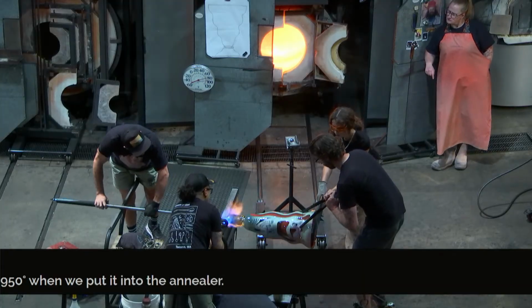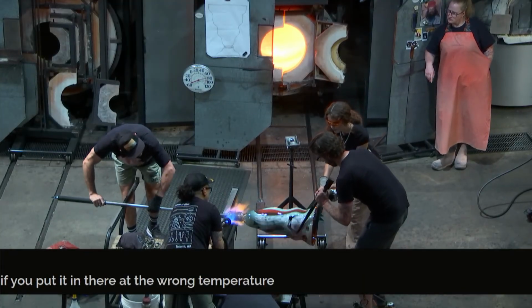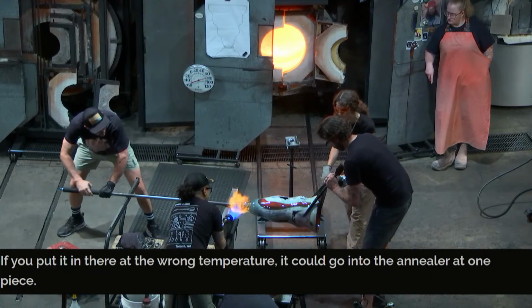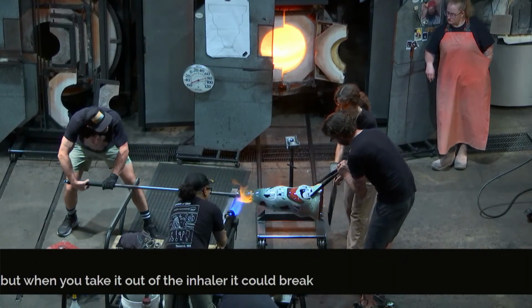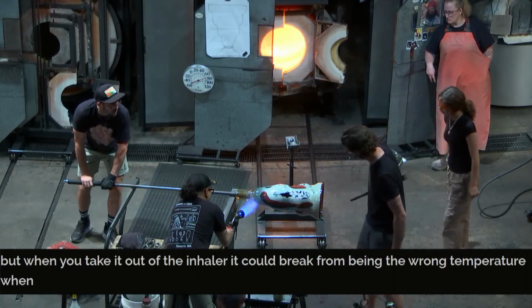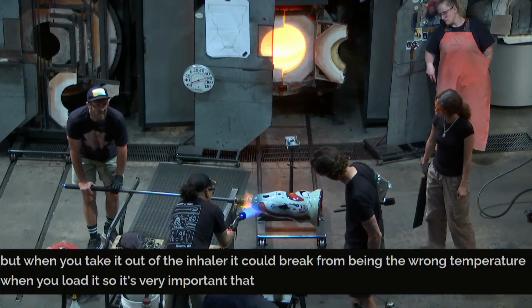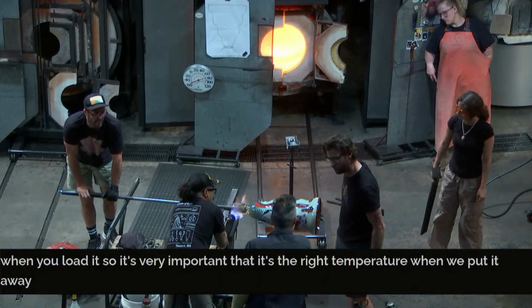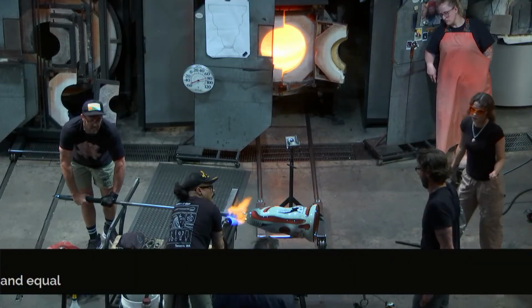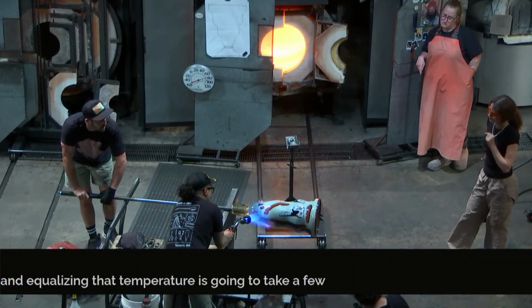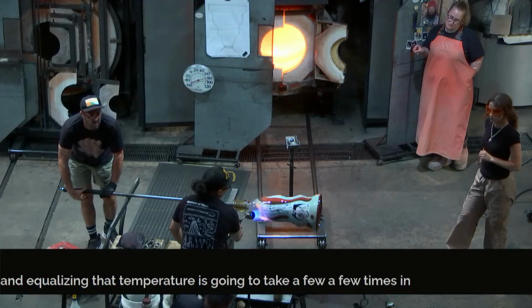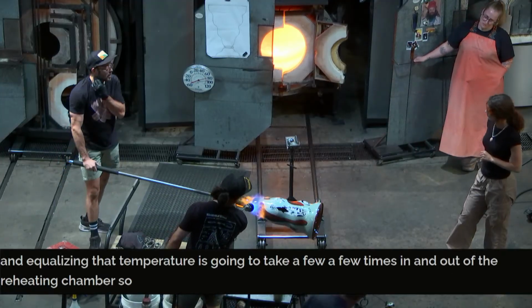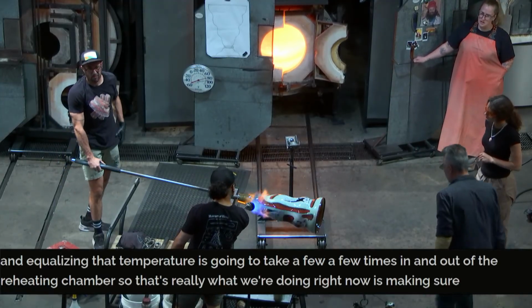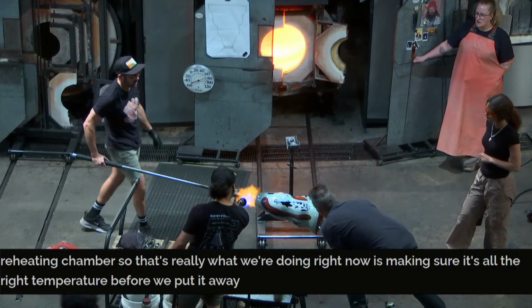If you put it in there at the wrong temperature, it could go into the annealer in one piece, but when you take it out of the annealer, it could break from being the wrong temperature when you load it. So it's very important that it's the right temperature when we put it away. And equalizing that temperature is going to take a few times in and out of the reheating chamber. So that's really what we're doing right now, is making sure it's all the right temperature before we put it away.